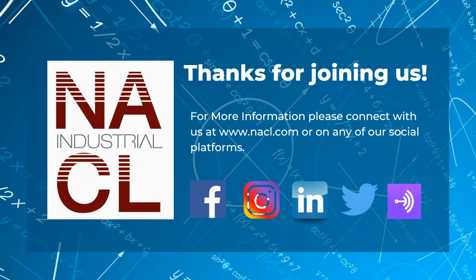Inspection-wise, the time and complexity of the specification is also going to drive your cost. If the requirement is telling you that ambient lighting and a quick visual overview in a short time period is sufficient, then I would say go with that, and that's going to be your least expensive option. If you require your coating to be inspected under magnification or have a very finite scratch dig requirement of maybe say 20-10, then the inspection time investment is going to be far greater, and the overall cost to produce your coating is going to be a lot higher because the inspection labor is amortized into the cost and you have more inspection labor. So that's really cost versus complexity and the impact on performance.